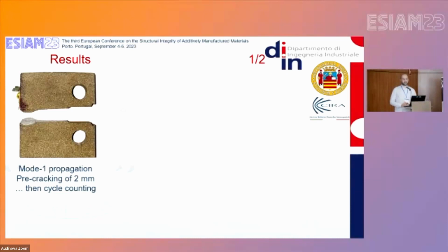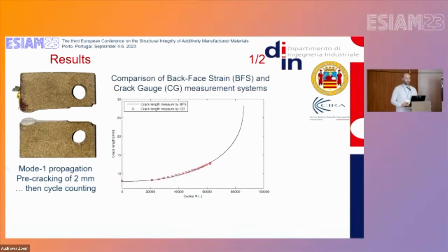We considered a pre-cracking of 2 millimeters, so we discarded the first cycles up to a crack length of 2 millimeters. Then we started the so-called cycle counting. Here there's a comparison of the crack length versus the number of cycles for the two measurement systems. We can appreciate a very good agreement between these two observations.